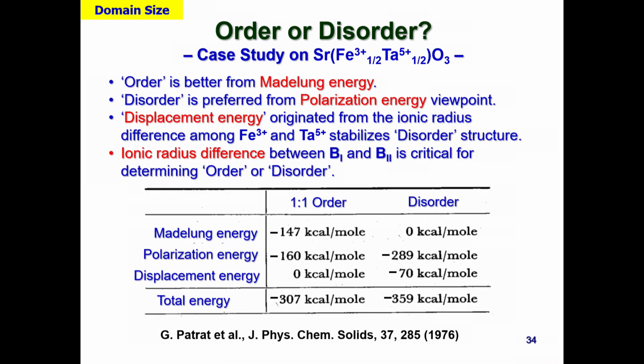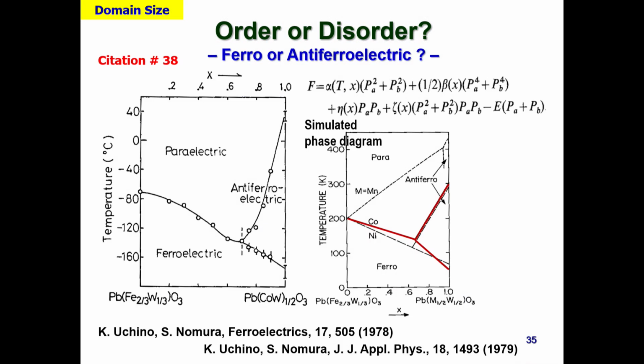So order or disorder, as you can roughly imagine, depends on the Madelung energy or polarization energy and the displacement energy, that means the two different ion sizes. So elastic energy is created. One example is strontium iron tantalate. In that case, the Madelung energy is definitely 1-to-1 order is lower, okay? However, for polarization energy and the displacement energy, disorder is better. Therefore, totally, this becomes disorder. And this is a typical calculation to estimate the order or disorder.